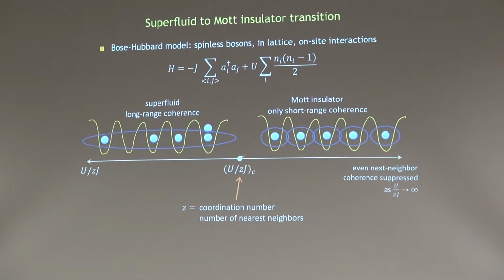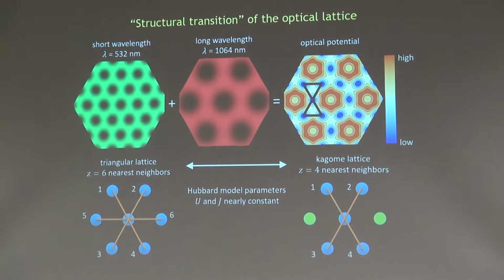And we know, from at least simple theories, we can easily calculate that this transition from the superfluid to the insulating state occurs at a critical value of this parameter. So U is the interaction energy per site, J is the hopping energy, and this quantity Z tells you how many nearest neighbors a site has within the lattice. So a lattice that is strongly coordinated with many neighbors to a single site would undergo the insulating transition only at stronger interactions, whereas a lattice that is very sparsely connected could undergo the insulating phase transition already when the interactions are relatively weak.